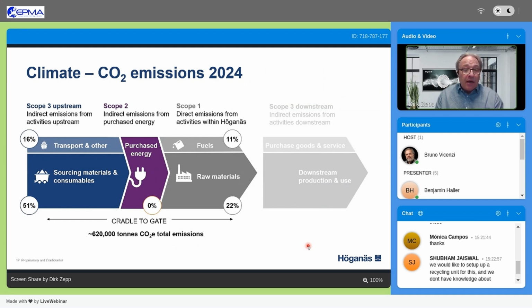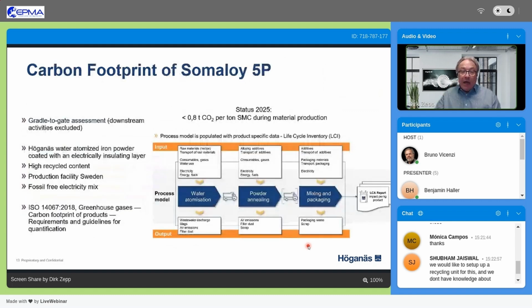Transportation and sourcing materials is of course the other side, and as I mentioned already, we are already above 80% of recycled material. But on the other side, we are trying to improve this. So we have a certain target within the next 4 years, 5 years, to get it at least to above 95% of raw material. And you see at the bottom that we have a total of 620,000 tons of CO2 that is already in the process to be reduced, but we still have a way to go. And once again, here a small overview of what the different levels are, from the water atomisation, the annealing, of course, to get the SMC material production ready. It all has a certain impact on the CO2 level.